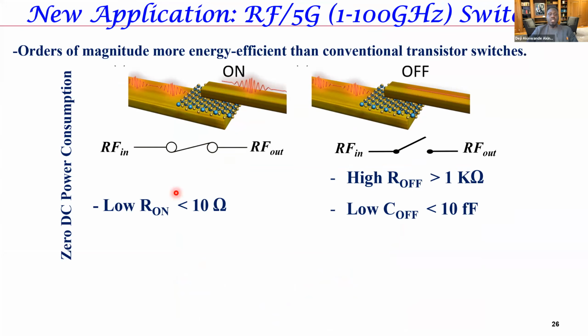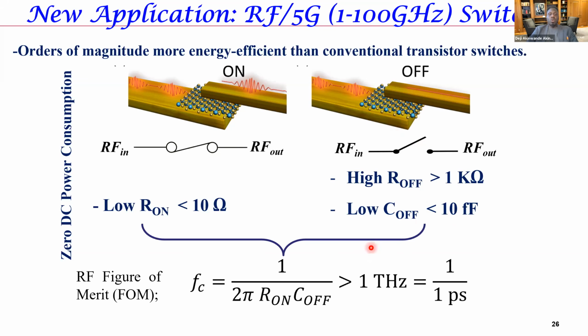The requirements are you need to be less than 50 ohms, because that's the standard resistance for radio frequency systems. So in general, you want to be less than 10 ohms, and in the off state, you want to be much greater than 50 ohms - let's say something above a kilo ohm. In the off state, it also behaves like a capacitor, so you want that capacitance to be less than 10 femtofarad. Altogether, for the radio frequency or 5G switches, you need this figure of merit, which is more or less an RC time constant. It needs to be greater than a terahertz, or less than a picosecond, to be interesting.